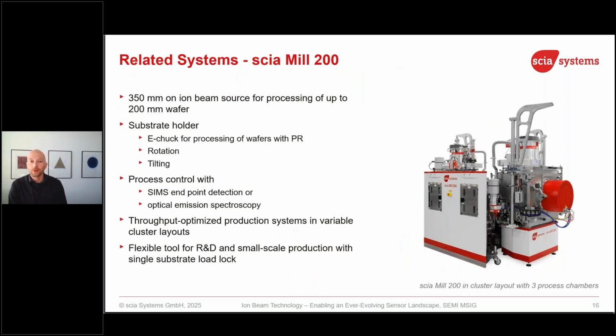The system we are using for such kind of processes is called the scia Mill 200. It has a 350 millimeter ion beam source, the big red device here, in order to etch a 200 millimeter wafer uniformly, with about 1% or 2% non-uniformity. We have electrostatic chucks inside with wafer tilting, wafer rotation, and of course this endpoint detection.